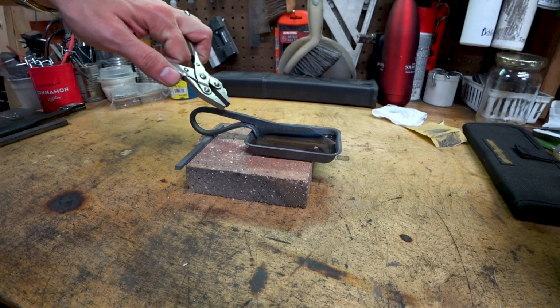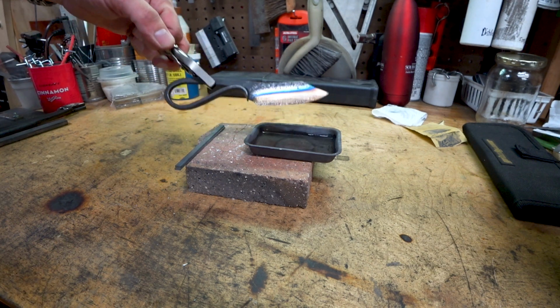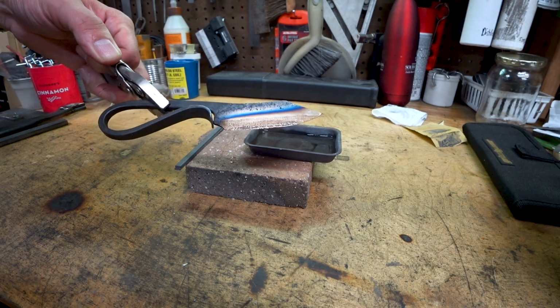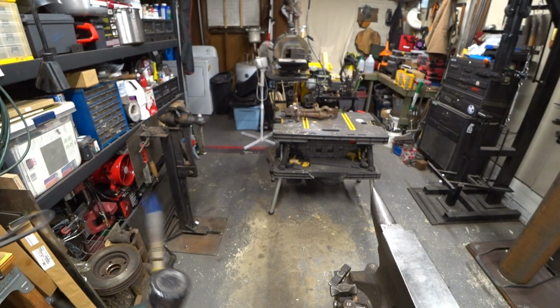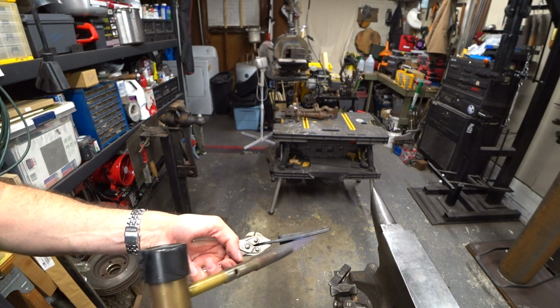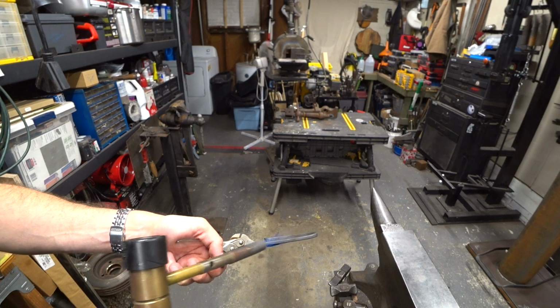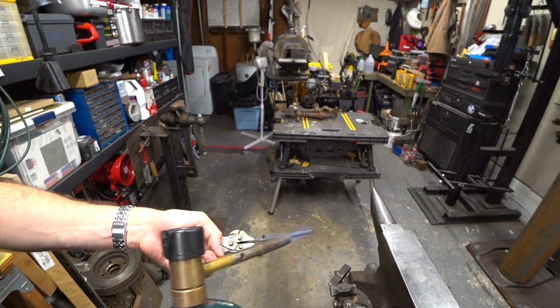So you can see a little more clearly here the temper lines. Everything below the line is the same hardness as it was before, around 60. And then everything above has been tempered back fully, and it's probably around 45 Rockwell.